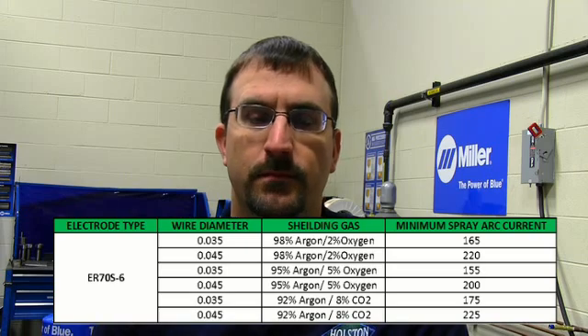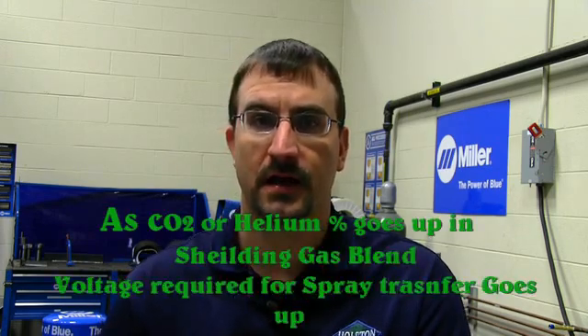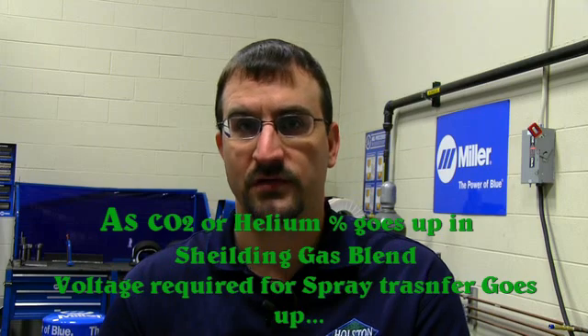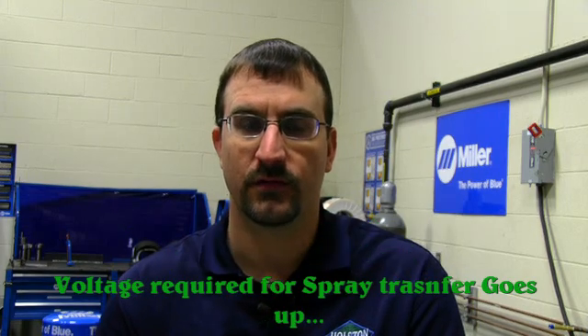So the last parameter that is necessary to achieve spray transfer is the voltage level. The voltage level is also going to change depending on the shielding gas and the wire diameter. So typically, it is necessary to have a minimum of 25 volts to achieve a spray transfer. So as the carbon dioxide goes up, so does the voltage needed to be in a spray transfer.